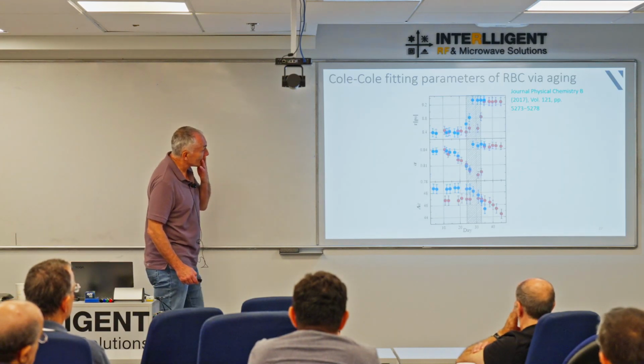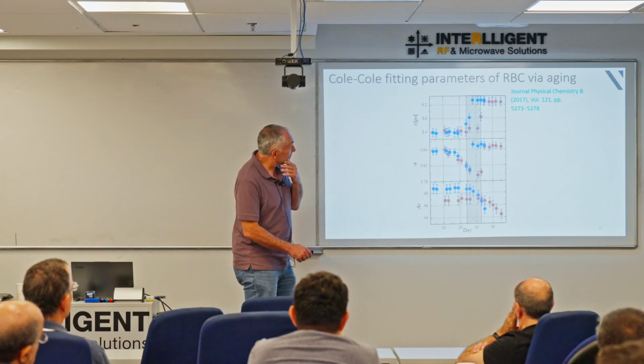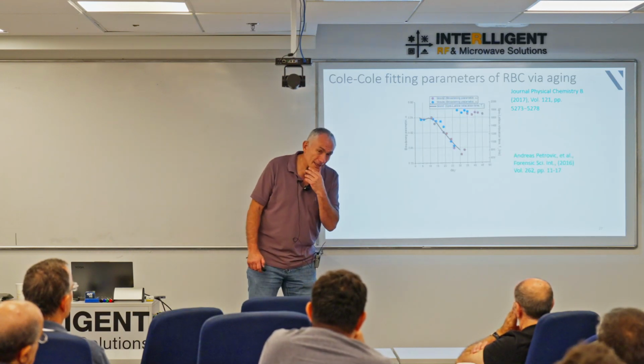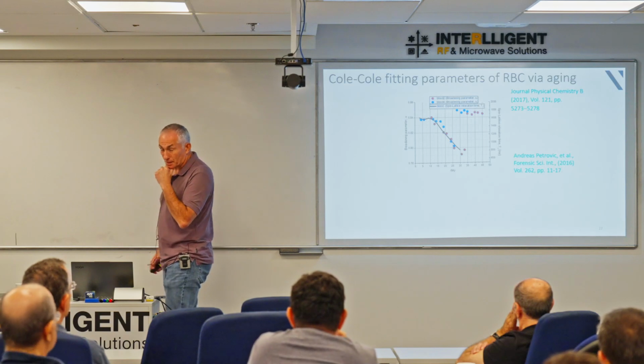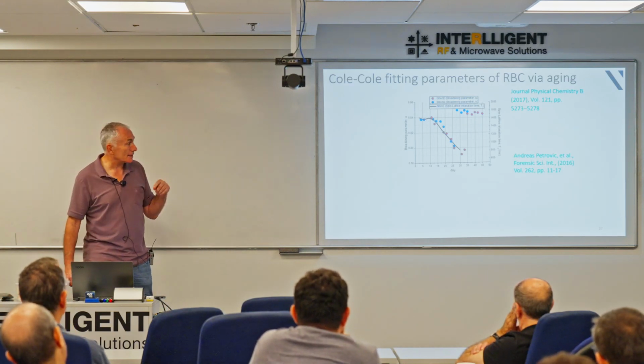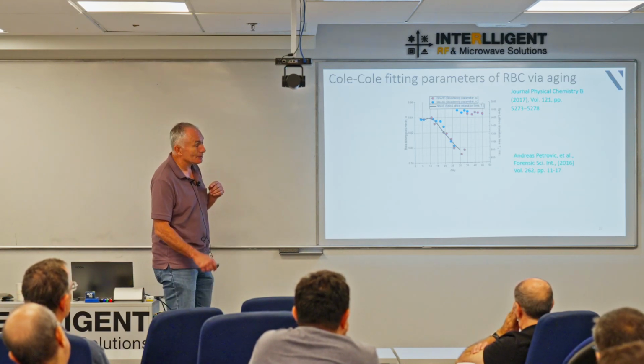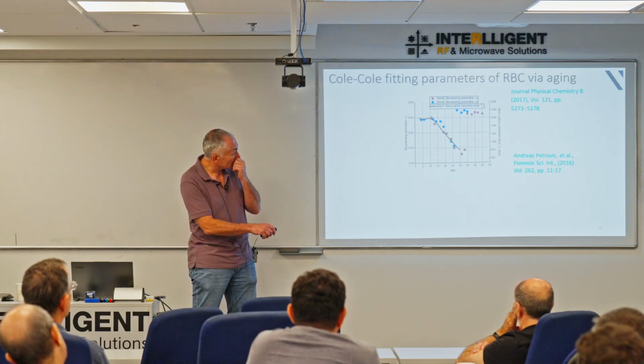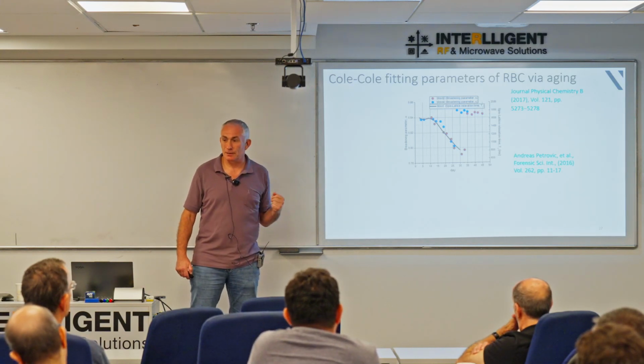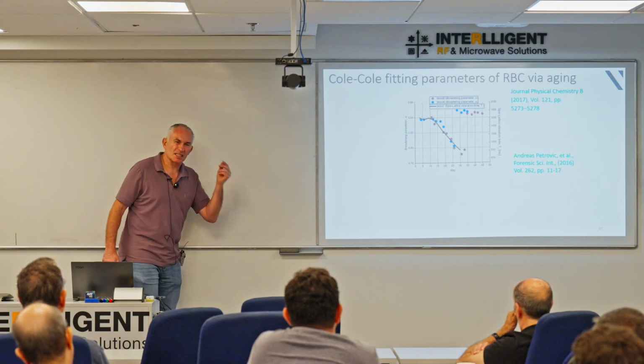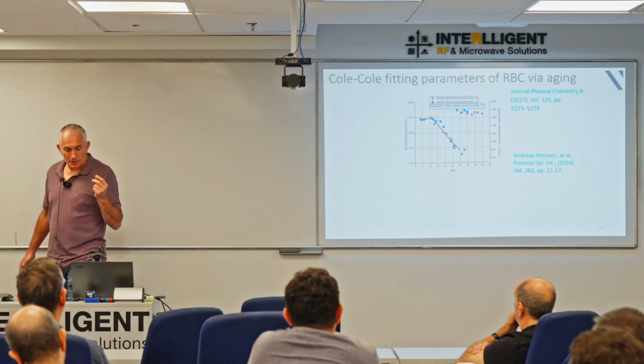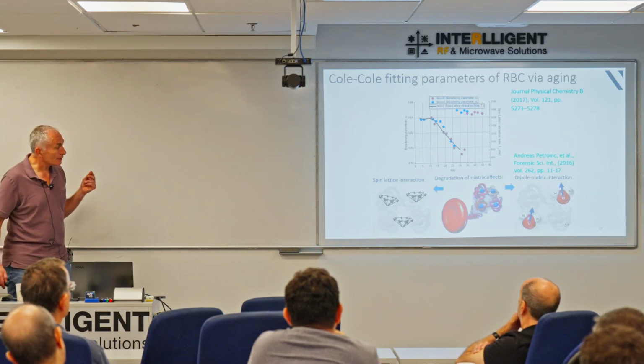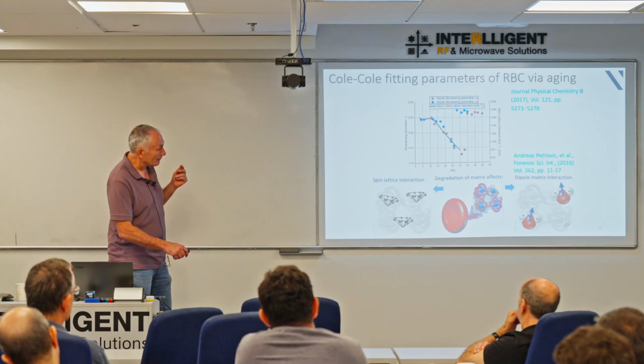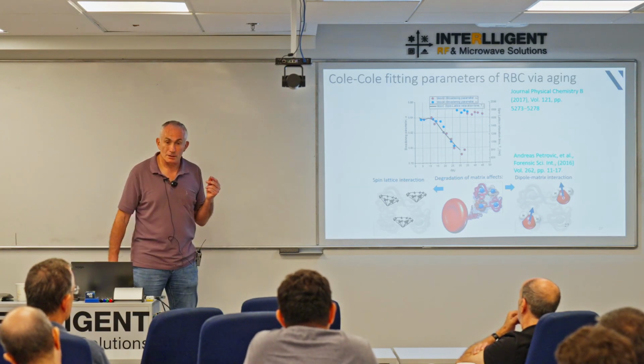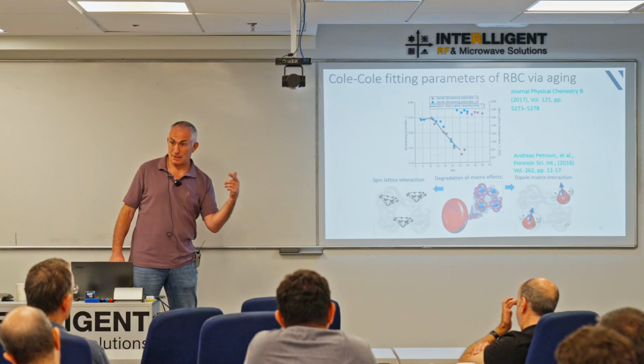Now, looking at this, we were able to find that other measurements have been made, particularly NMR, where they're looking at the spin lattice constants, and they'd noticed exactly the same behavior. That's that black line. So we had confirmation here. We have confirmation that what we're seeing is something real, that something is most definitely changing. And it is basically the fact that the spin lattice constant is reflecting what's happening to that skeleton itself.